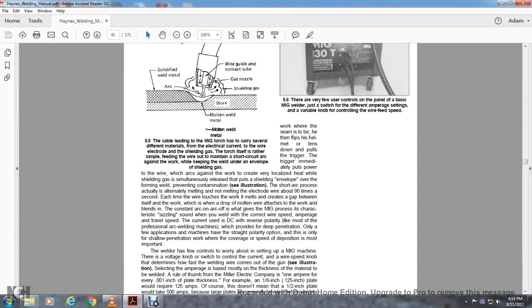The short arc process will actually alternately melt and not melt the electrode wire about 90 times a second. Each time the wire touches the work, the balance of the current creates a gap between itself and the work, and when it drops, the molten wire attaches to the work, and the arc goes on and off, which gives the MIG process its characteristic sizzling sound. Wire speed, amperage, and travel speed are characteristic, and the current uses DC reverse polarity.